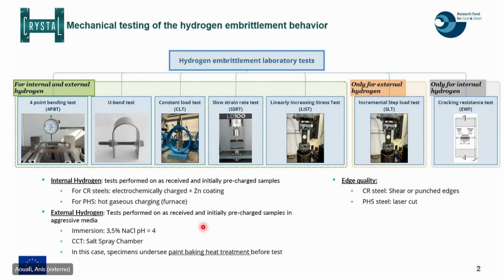For external hydrogen, we have made the choice to use two different media. The first one is immersion in salt water with pH 4, and the other one is a cyclic corrosion test which simulates a salt spray chamber. So for the external tests, it's worth mentioning that all the tests undergo a baking heat treatment before testing in order to be representative of what the real part on the vehicle sees during the life cycle of the material.